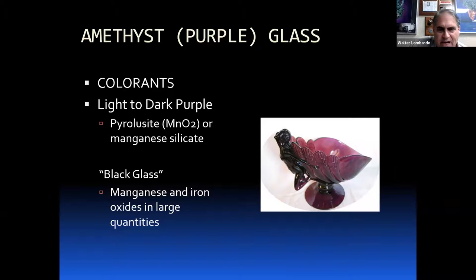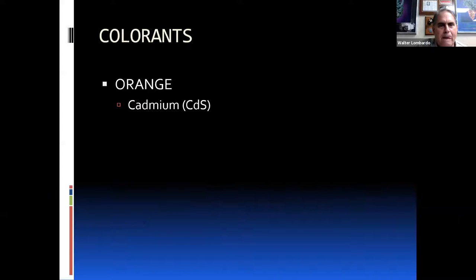If you want to make black glass, there's really no glass that's truly black. It's actually a very dark purple. So you can take a glass that looks black and put an intense light up to it, and it's a dark purple. And that is using large amounts of manganese and iron oxides, which will cause that very deep, almost black color, at least in appearance.